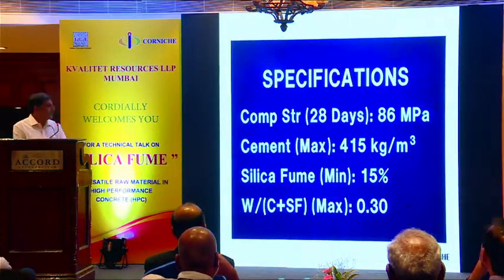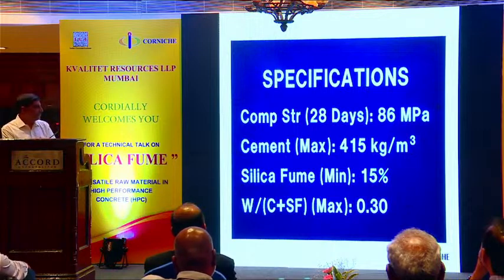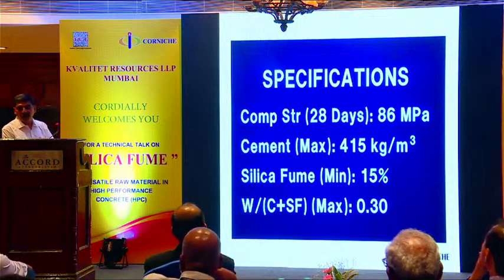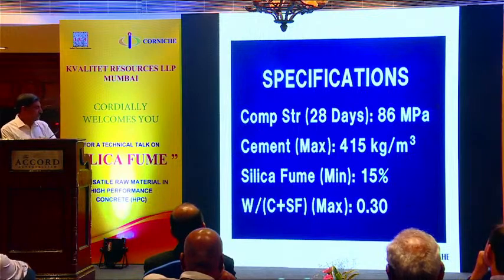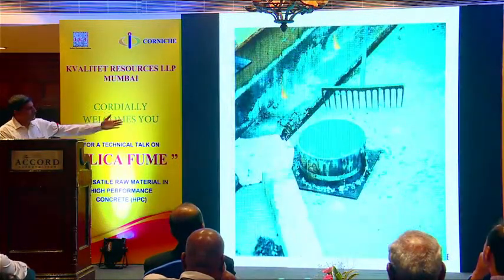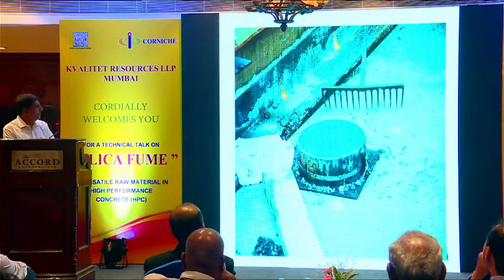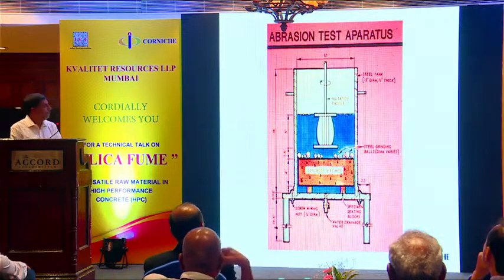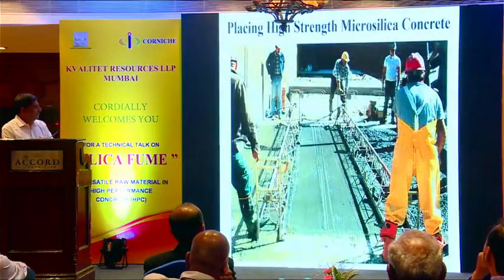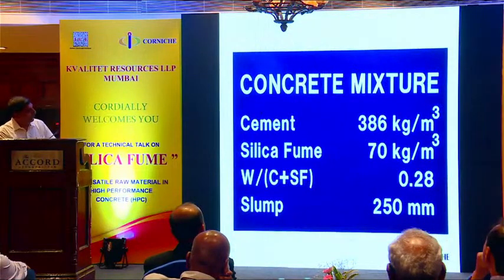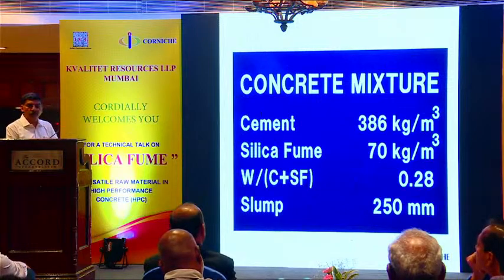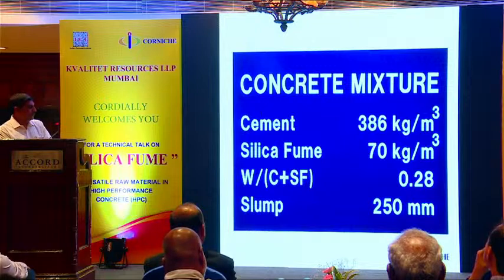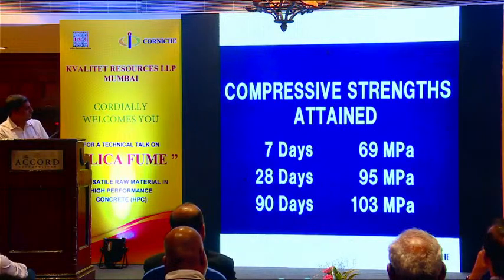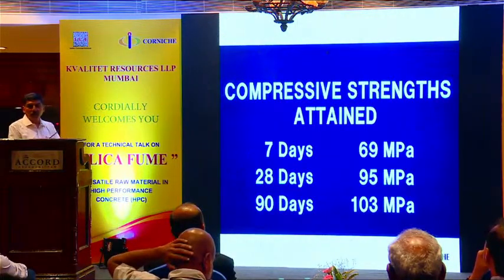Specification, finally, what they did was, they wanted more than 80 megapascals. Cement, maximum 415 kg. Silica fume, they said minimum 15%. As a salesman, I'll be very happy to sell more silica fume. And water binder ratio was 0.3. This is in 1985 in the US. This is a sample actually that they took for testing. This is the equipment. Ultimately, what they used there: 386 kg cement, 70 kg silica fume. Water binder ratio 0.28, 250 mm slump minimum. The results: 7 days 69 and 28 days they were hitting 95 megapascal, even with the local soft aggregates.